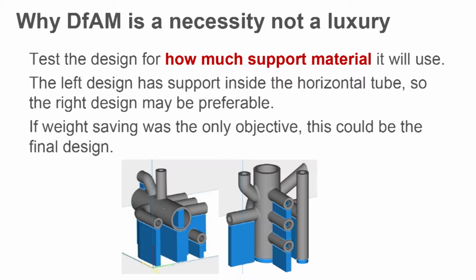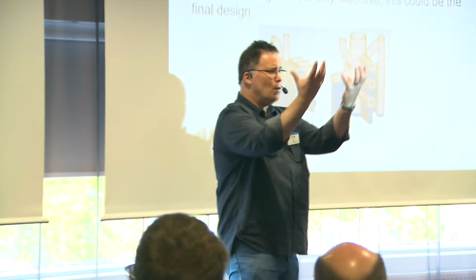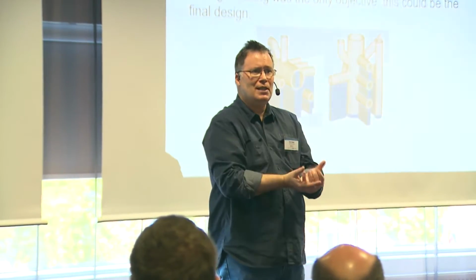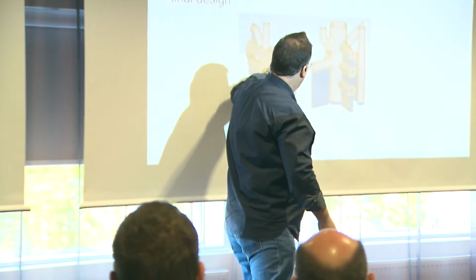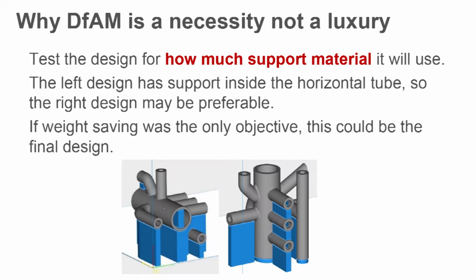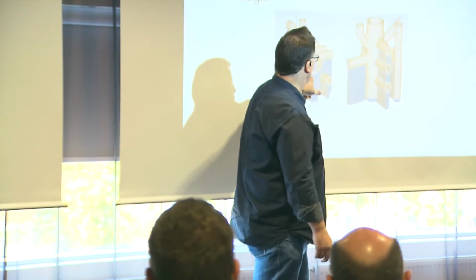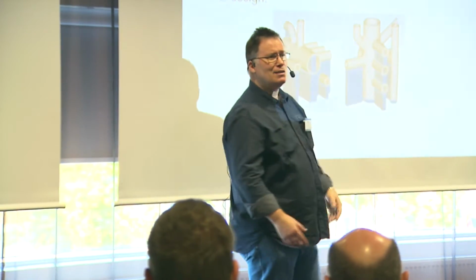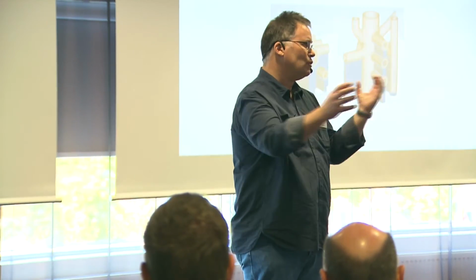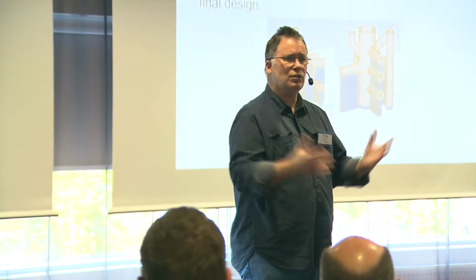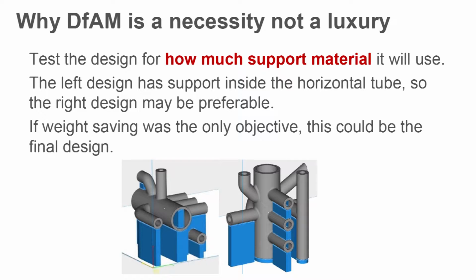So for those of you not familiar with metal printing, you've got to anchor your part to the platform so the heat doesn't distort the whole part. This is the support material that is needed to weld the part to the platform. Now, nothing wrong with either of those designs. You might argue that if there's no reason not to, this orientation is maybe better than this orientation, because here you've got support material inside the part and removing support from internal structures is much harder than from outside structures. Therefore, you could argue that the right-hand design is maybe better, but there may be a reason where the left-hand design is actually the better one, depending on your functionality.